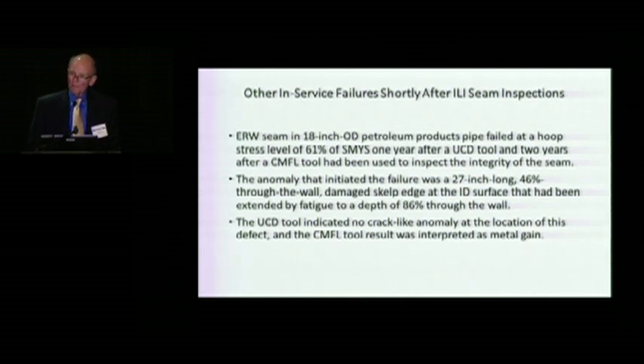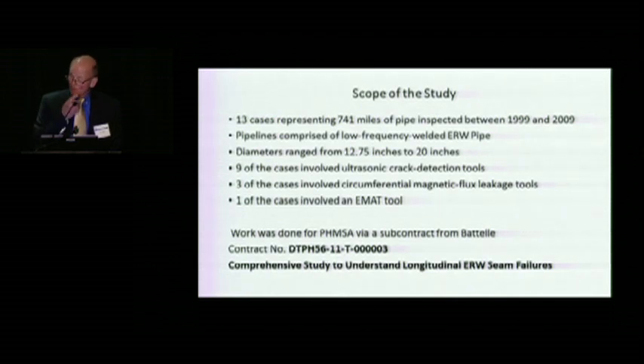Now, granted, some of the defect in a year could grow, but these were huge defects to begin with. So it's kind of hard to see why they shouldn't have been picked up. Well, as far as the study goes, we looked at 13 cases, not representing a whole lot of pipe, but one of the reasons we had a limited amount of data has to do with the fact that it's hard to get data because by the time a company wants to donate data and they pass it through their legal system, they get rejects sometimes.